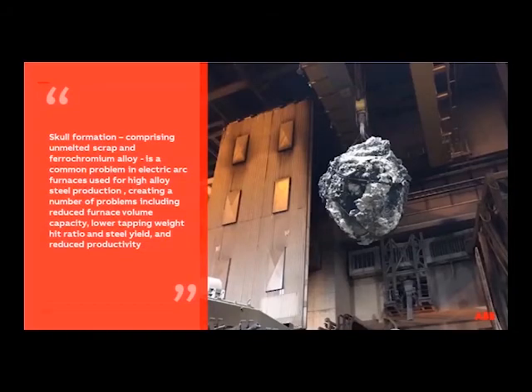Now, another serious problem for the EAF operator is the furnace so-called build-up or skull formation, which normally happens when melting special steel or big scrap sizes, and also other high melting alloys like ferrochromium and so forth. This creates numerous problems for the electric arc furnace operator: reduced furnace volume, for example lower tapping weight, yield loss, refractory problems, and also reduced productivity.